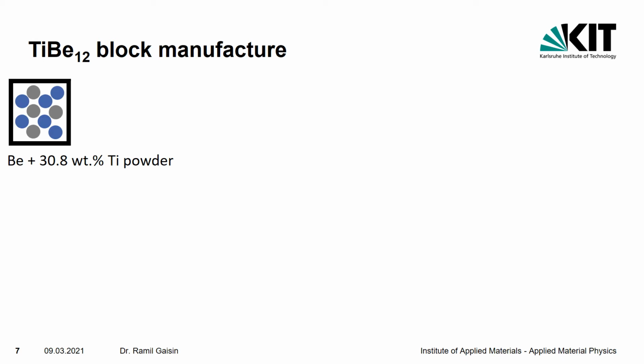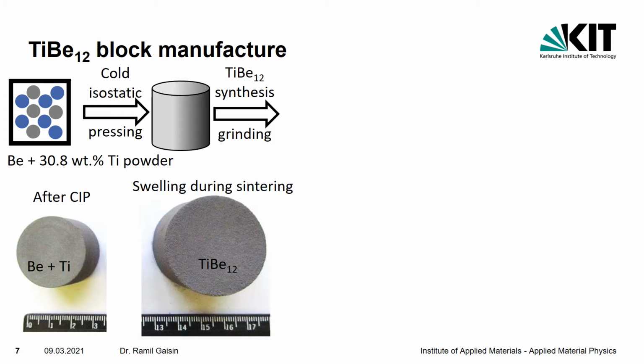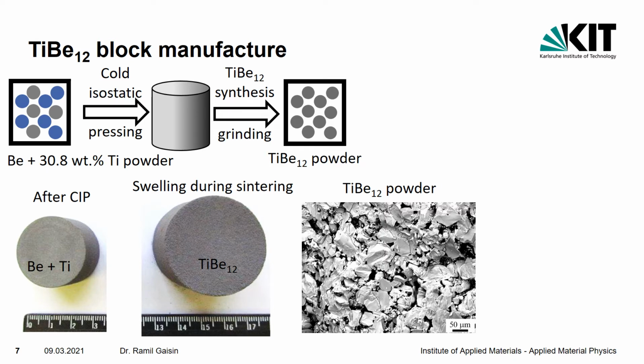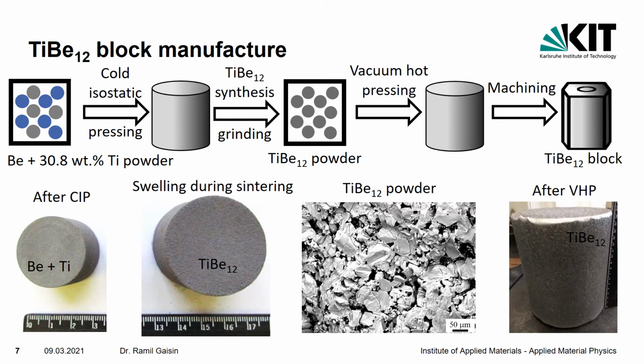In the new technology developed in Ulba, pure beryllium and titanium powders are blended together and pressed at room temperature into such tablets. During the following beryllide synthesis, these tablets swell intensively, forming a porous material with a low density. But this beryllide can be ground to titanium beryllide powder. And in the next step, vacuum hot pressing of this powder results in a solid, dense material, which can be machined to its final size and shape.